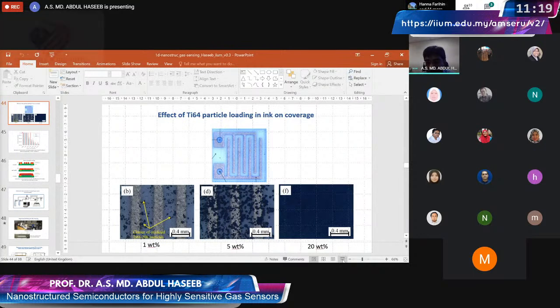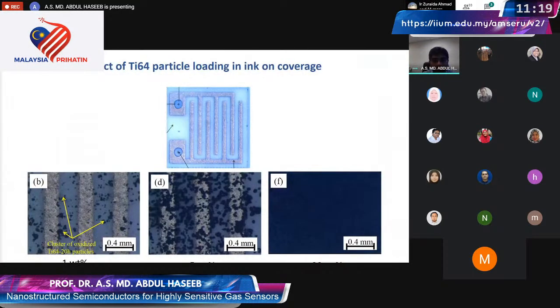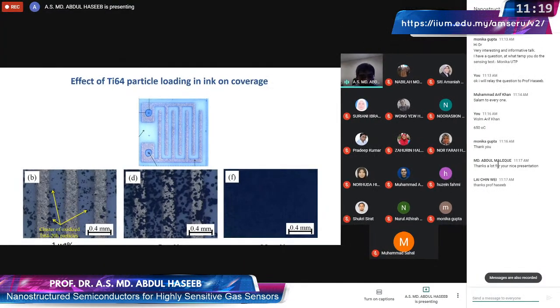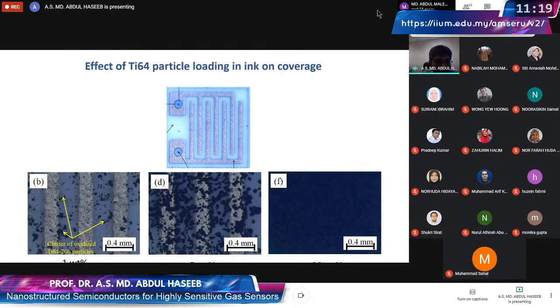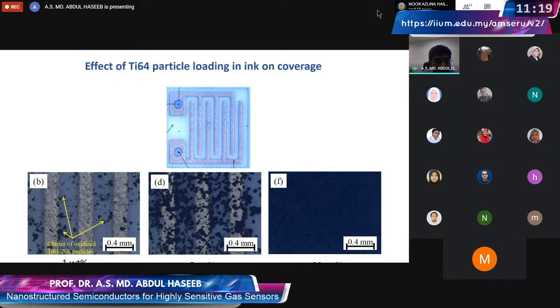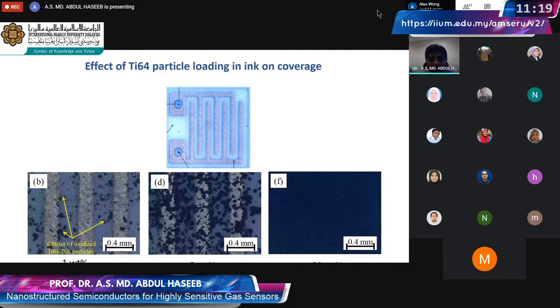And if you see this, let me highlight this. The way they are arranged on the surface of this electrode depends on how much solid you put into that carrier vehicle of the liquid. If it is too small in amount in the original liquid, then you don't have continuous connection of the layers. The particles do not bridge, so you don't get any signal. What we need is enough particles that are more or less statistically randomly distributed, and they are connected at different places randomly, and they create, in effect, a continuous conduction path. So that is how we ensure it.